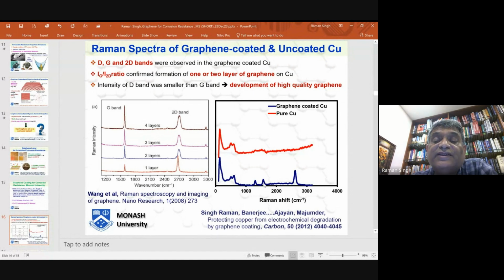But this spectrum also gives me another very important piece of information. The ratio of the intensity of G and 2D peaks gives me the number of layers of graphene. For single layer graphene, the G peak is shorter, dwarfer compared to the 2D peak, whereas if you increase the number of layers, the G peak becomes taller and taller with respect to the 2D peak. In our case, we had single layer graphene because the G peak is shorter compared to the 2D peak. And of course, the pure copper does not show these peaks. This other little peak is the D peak, which gives me an idea about the defects in graphene.